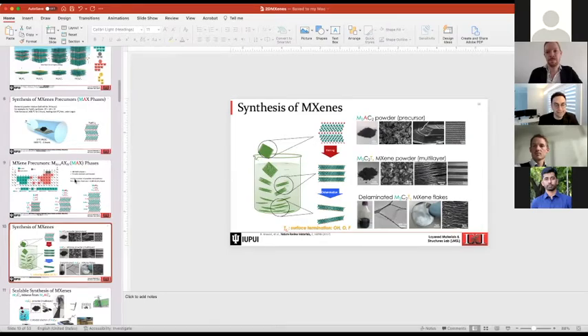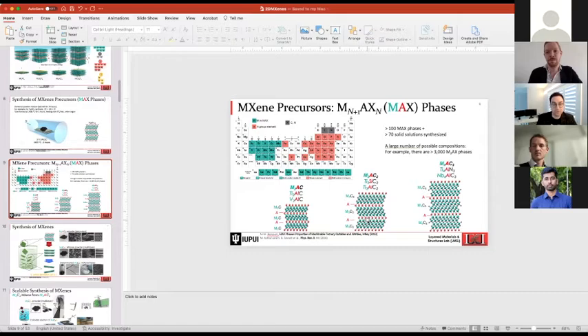Now, even more relevant is the synthesis of molybdenum 2C. Mo2C is synthesized by adding gallium, and you start with the hexagonal Mo2C. So that is layered, you might say, which is true, but at least for now, it is impossible to delaminate or exfoliate Mo2C to single sheets. So by adding the A layer, which in that case is gallium, we create again a layered structure like this, where we have two layers of transition metal with carbon, spaced apart by these A layers. So the addition of these A layers is needed to create a new structure that can be used as a precursor of MXene. That's why we add the A layer and then later on leach it out. It's a new phase formation by adding the A layer.